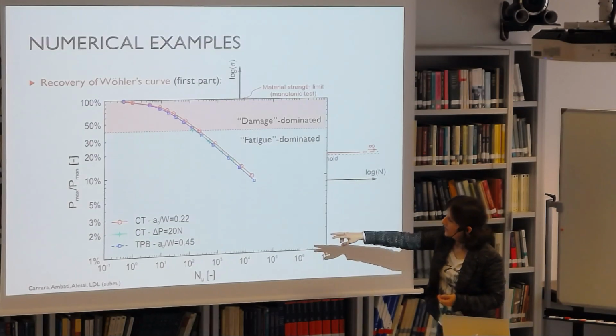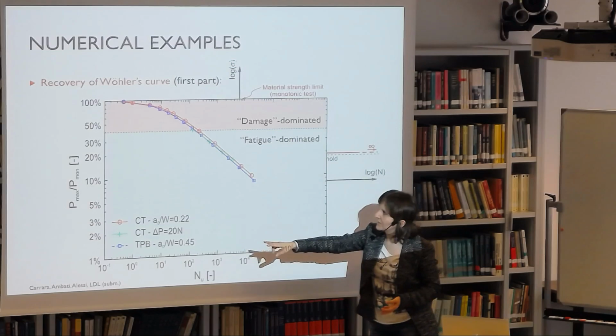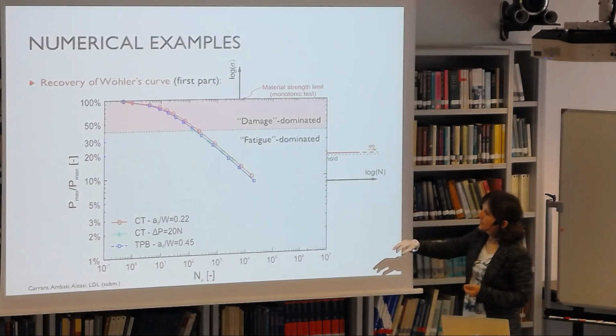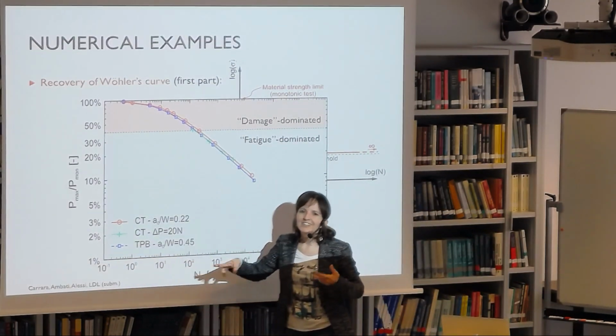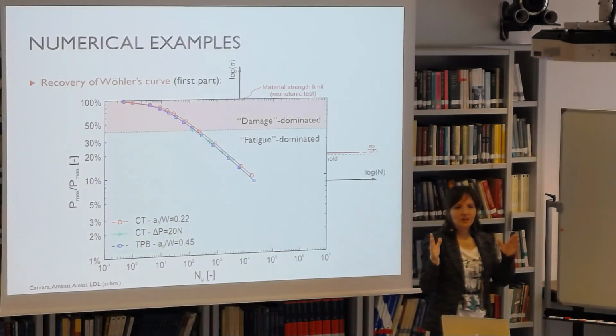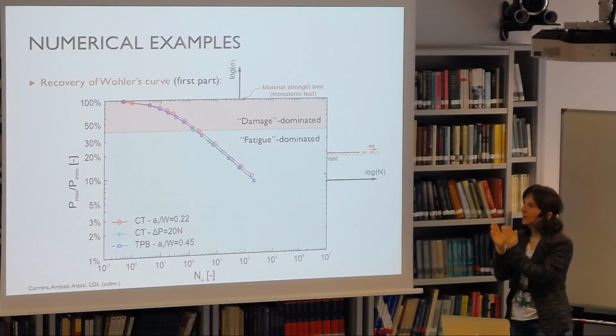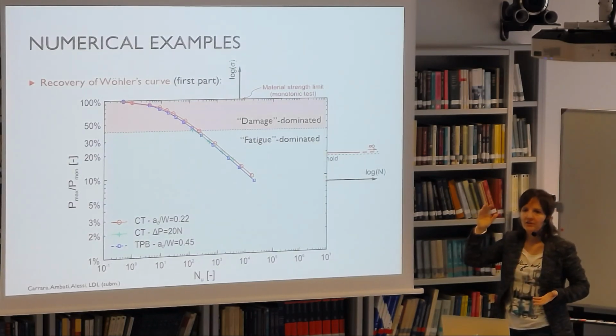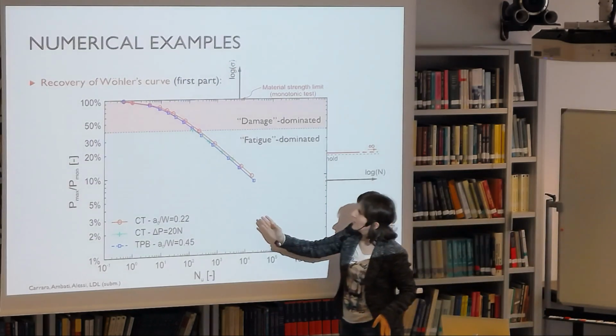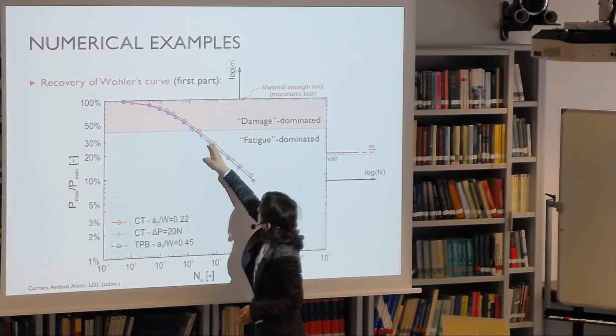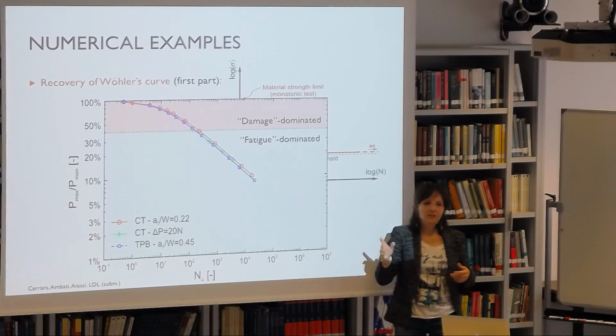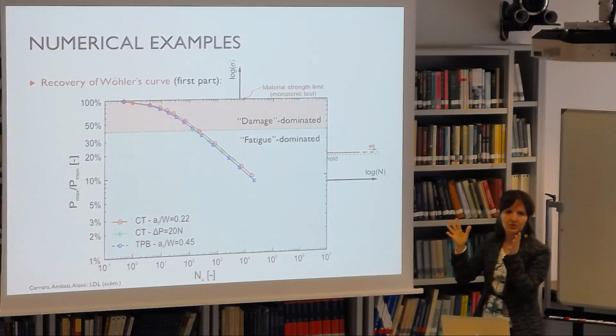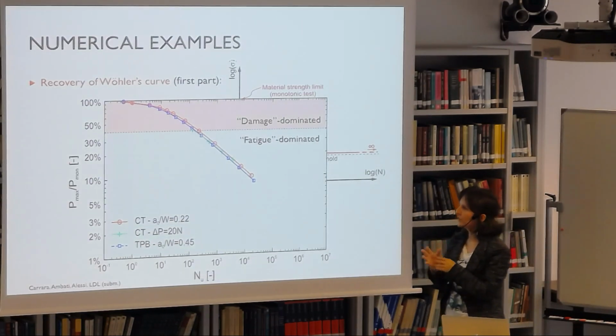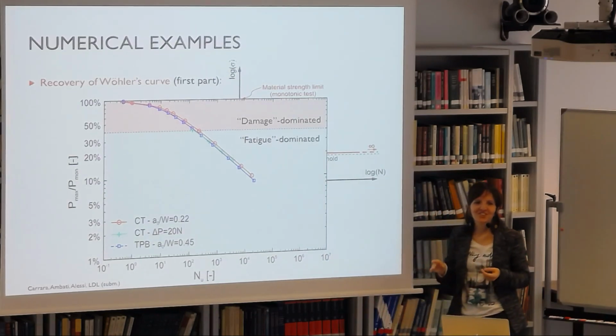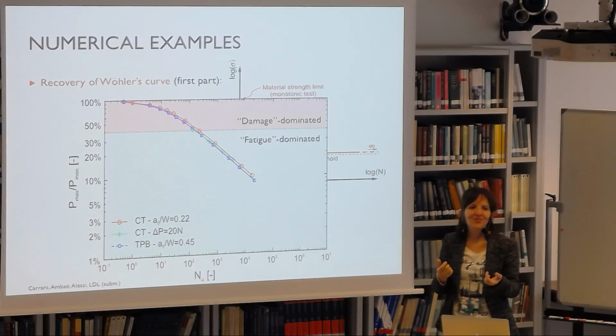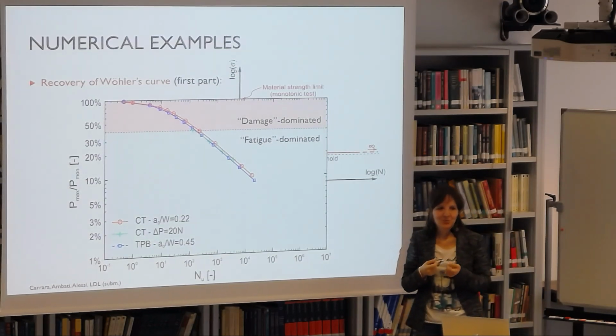So if we apply very large loads, we can sustain a limited number of cycles, and this is the area that we call damage dominated, in the sense that this area is static damage dominated. So the stable crack propagation phase, the central portion of the Paris curve, is very, very limited because the stress is so high that you get failure very soon. But if you apply smaller loads, you are in this area, which we call fatigue dominated, meaning that you have a fairly large Paris domain, so a very large fatigue stable crack propagation phase. And what we don't have is this final part, and the reason is very simple: computations are very expensive, because so far we've been running every single cycle, but we are working on it right now.